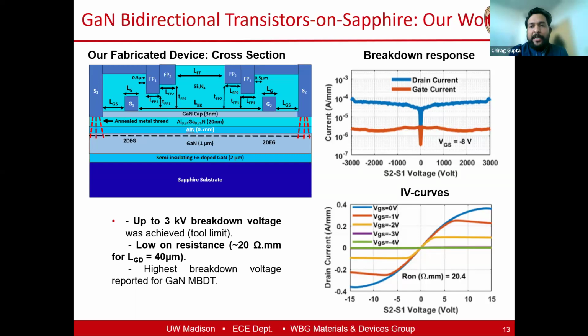We fabricated this device, and again, you can see that the bidirectional performance is there. It's symmetric across first and third quadrant. We were able to get reasonably low on resistance, and this is what we expect, right? Nothing too out of the ordinary. Basically, for 40 micron gate-to-gate spacing, this is written LGD, but it's gate-to-gate spacing, we were able to get 3 kilovolt breakdown, and as you can see, the device is not catastrophically broken yet. This is due to the tool limits.